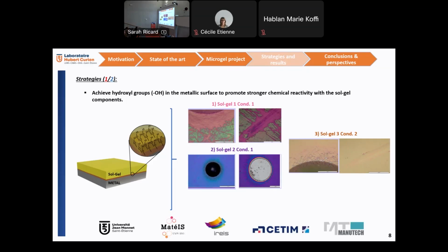However, employing this strategy in sol 2, condition 1, you have good results for the Rockwell indentation. Here you can see a small fissure close to the area, but it is normal because we are using a lot of load. And here you are able to find a well-defined calotest to be able to measure the coating. And a good result for sol 3, condition 2, the normal fissure close to this area, but you cannot see any delamination in the sol. I would like to say that we should study for each sol and each condition how this strategy is working.